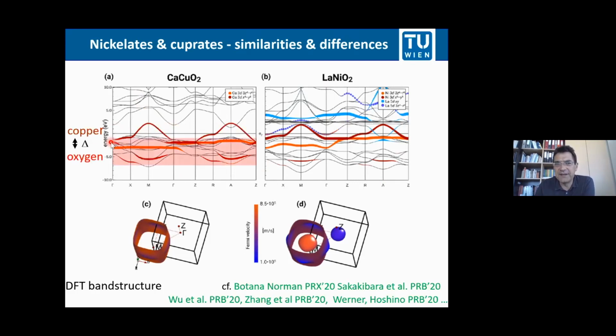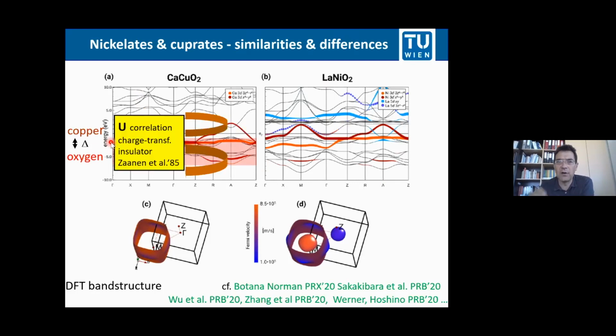But just beneath it, with a very tiny charge transfer splitting, is the oxygen band. And that means if you go beyond DFT and now include electronic correlations, as Zaanen, Sawatzky and Allen have proposed, you form some Hubbard bands instead.